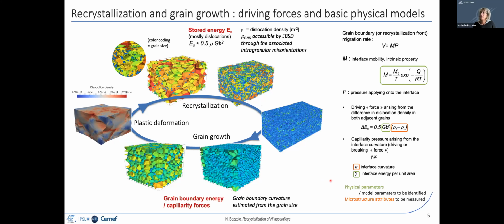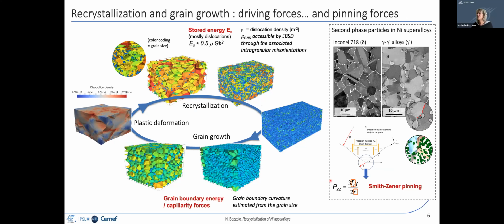In nickel-based superalloys, I've already mentioned that we have second phase particles which are in there in order to pin the boundaries and avoid the grains growing too large. The interaction between a grain boundary and the second phase particles is the so-called Smith-Zener pinning phenomenon, which proceeds by a capillarity interaction between the particle and the boundary. So there is the Smith-Zener model, which allows for describing a kind of pinning pressure, which counterbalances the driving force and so brakes the boundary movement. You have here the expression.